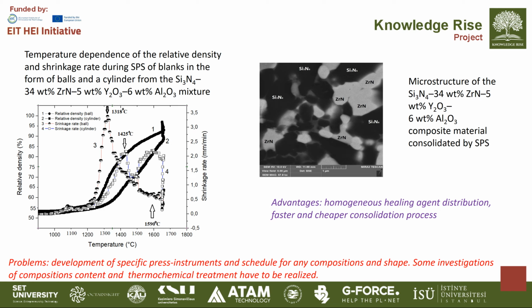In conclusion, we can say that SPS consolidation for these materials successfully produces dense, homogeneous microstructures with a well-distributed healing agent. The observed densification and shrinkage behavior confirms the efficiency of these methods for fabrication of high-performance self-healing ceramics. However, further development of custom press tooling, optimized schedules, and thermomechanical processes is essential to adapt the method for various compositions and geometries. These improvements will ultimately enable scalable production of reliable self-healing materials for aerospace, energy, and advanced mechanical systems.